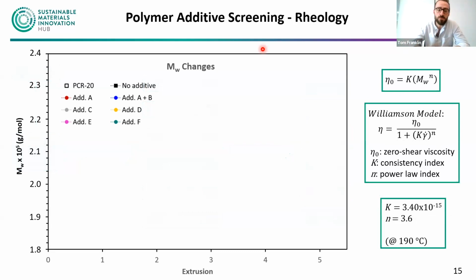But we can go a step further. We can actually look at what's known as the molecular weight. The simplest way to think of that is effectively how long our polymer chains are, in quite a much simplified definition. But effectively, if we have molecular weight changes, we know something is happening to our chemical structure. If the molecular weight decreases, we know that we are getting chain scission, one of those degradation mechanisms we discussed. If we get a molecular weight increase, we're getting chain branching, which is that second degradation mechanism, as discussed. And for polyethylene, branching typically dominates. So if we see an increase in molecular weight, we can be fairly confident branching is happening, but we know there's a change on that molecular structural level.